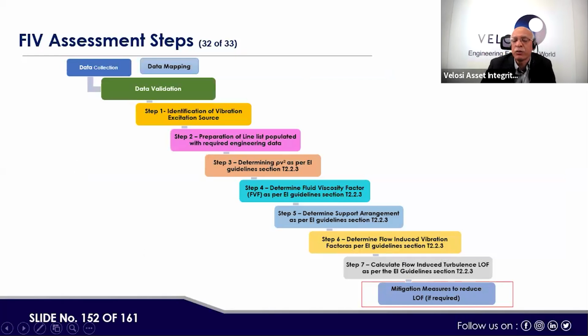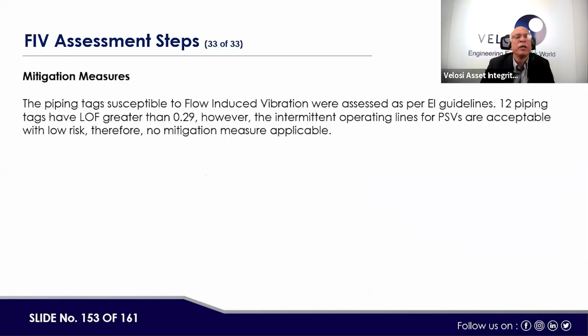Last, mitigation measures to reduce LOF if required. Here the pipe tags susceptible to flow-induced vibration were assessed as per EI guidelines. 12 piping tags have LOF greater than 0.29. However, the intermittent operating lines for PSVs are acceptable with low risk. Therefore, no mitigation measure or change was recommended.